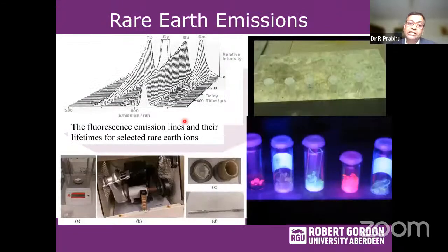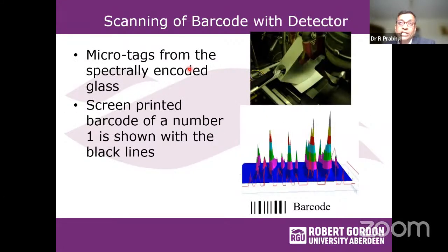Now, in addition to that, these multi-doped glasses have their own lifetime spectra based on the doped elements. Now we have developed multi-doped glasses and single-doped glasses, and in principle, they are nearly transparent. They are glass. And under UV illumination, you can see all the glasses are fluorescent now. And if you look here, some of the powders we made from the glasses were made using a ball milling process. So micro particles of this glass were made using the ball milling process. And these microparticles are the spectral signatures, or microtaggants. And these microtags were spectrally encoded inside the glass. So each microparticle has its own spectral code.